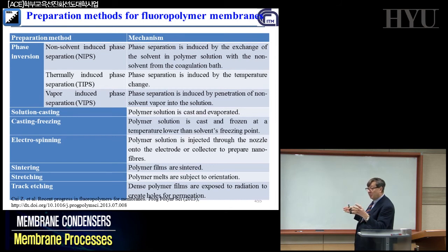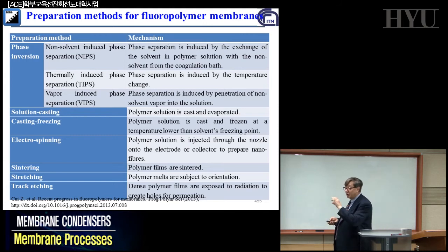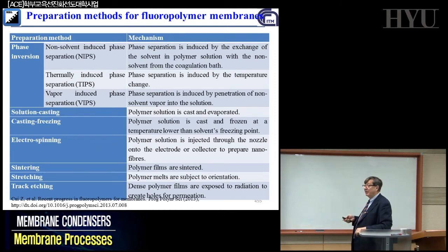The final performance of your membranes are in part related to the TIPS effect and in part related to the NIPS effect. And that can change you, for example, the distribution of the final morphology of your polymer in one of the polymorphs which exist. Typical case, that is the case of some PVDF that can exist, we will see in 4 or 5 different configurations. And this different configuration can be present in your final membranes on the dense key, on the upper part, on the bottom part, in the center, and you can change the percent of this polymorph playing with NIPS, TIPS, or other kind of inversion.